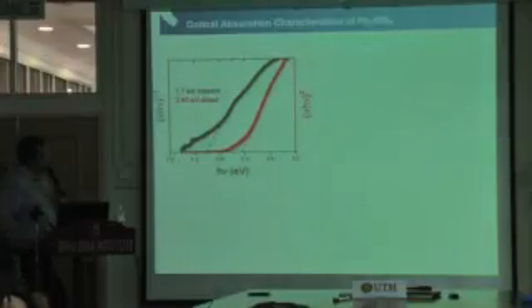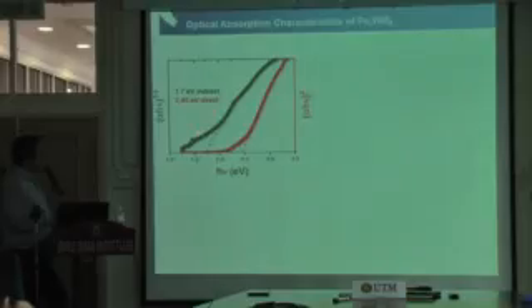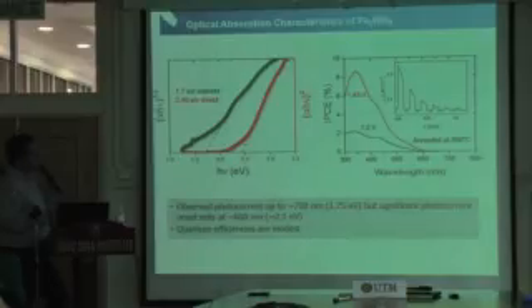We checked the optical absorption characteristics of our film. Indeed, we get 1.7 electron volts for the indirect band gap, and the direct part of the band gap is 2.45. The quantum efficiency is modest, pretty low actually, only about 9% here. And the photocurrent onset here is only at 600 nanometers, so that's 2.1 electron volts. Although if you zoom in on this part, you can see something, which means it's active up to 1.75, which is the band gap, but significant photocurrent only happens over here. This is related to the indirectness of the transition, the indirect band gap of the iron tungstate.